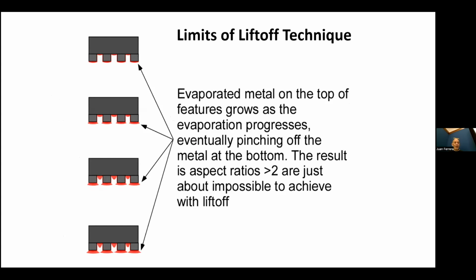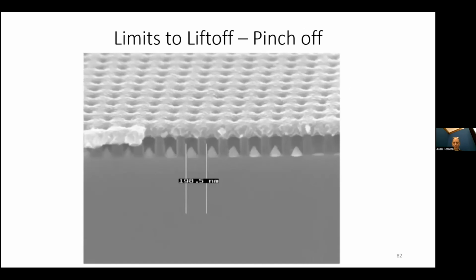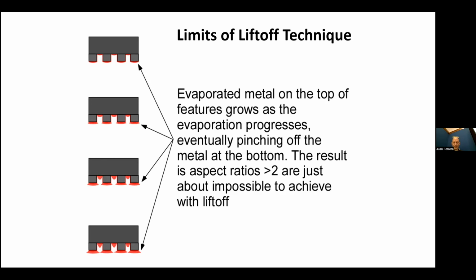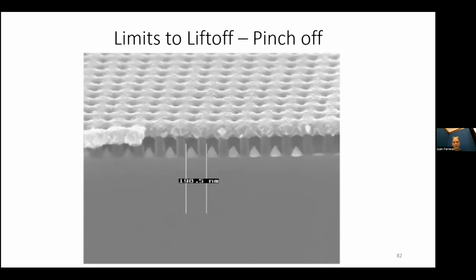There are limits to E-beam evaporation though, and that is that you typically can't lift off any more than half of your resist thickness, because as you evaporate, this red stuff gets bigger and bigger, and it accumulates at the edges, and it makes these little mushroom caps until you get something like this. And that's typically going to happen at about half when you try to get more metal in your slots than you have room for.